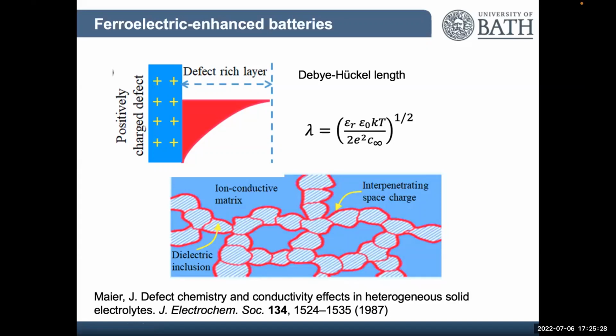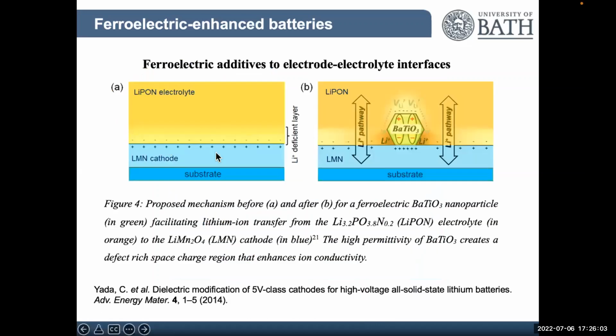Some materials it's 3,000-4,000, some other materials up to 40,000-50,000 relative permittivity, even very high, certainly even when you're close to the Curie temperature. So there's certainly some interest in adding ferroelectric additives, not really due to the piezo or pyroelectric effect, but really exploiting their very high permittivity properties and the large space charge regions, especially when those inclusions begin to coalesce and to percolate through the system. And this is just some work from the literature by Yada.